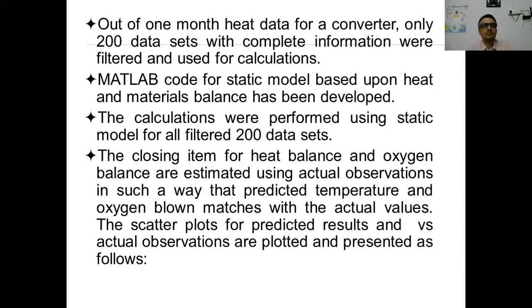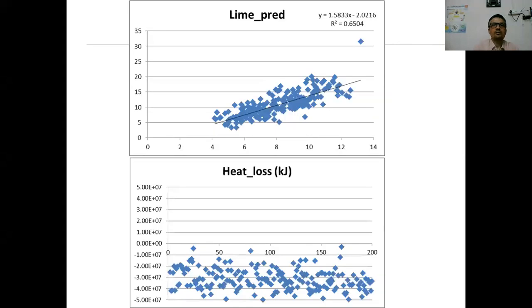So we have collected one month of heat data for a converter, and then we have used MATLAB coding for development of a static control model based upon the heat and mass balance. Out of those data, we have collected the sensible data. And then by using those data sets, we have calculated a closing item for heat balance and oxygen balance. Then we have matched those discrepancies with the actual observations, plotted them and presented them. So for the lime prediction, it is giving an R square of 0.65. Lime prediction is being done in a very reasonable manner.